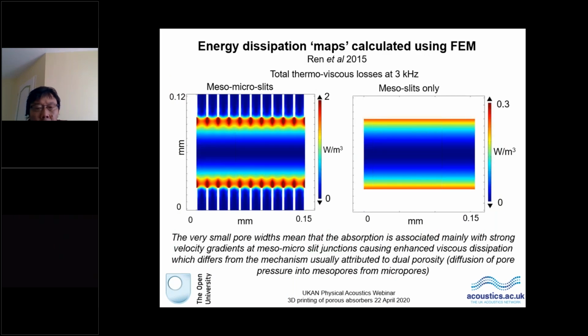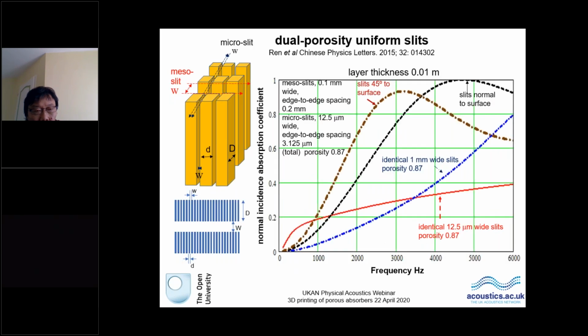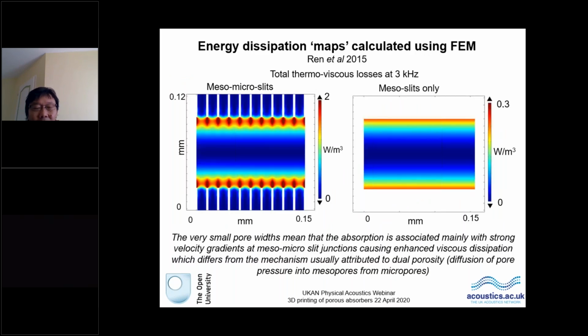They also did some FEM analysis, and here I'm showing one of the plots that they got, which is quite interesting, and it shows that there are things that could be investigated even further that are going on at the junctions between the micro slits and the meso slits. In fact, the analytical results that I showed before, how do I go back? Yes, these analytical results are based on treating this as a dual porosity material, and Olga, for one, doesn't believe this is true, but nevertheless, that's what they did, and their FEM results show that there are interesting things going